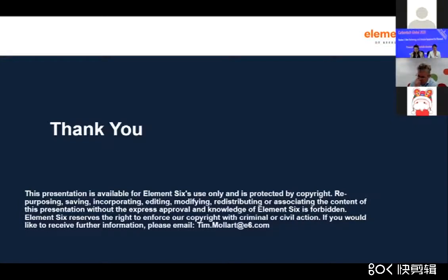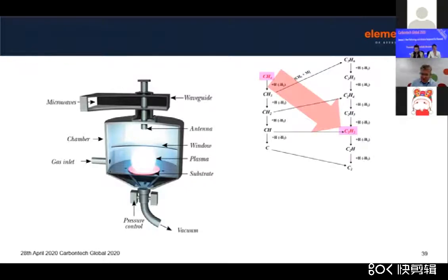Thank you. Well, I think I'll come to a couple of points here. The advantage is that it gives you very high control over the purity of the diamond that you're producing, and for some applications, even in polycrystalline diamond, that is actually very important. And I think the advantage, as the schematic for our reactor would show you, is the fact that it's electrodeless. So essentially, you can reduce the contamination that you get from other types of discharge system, and also, as I say, the intensity of the plasma gives you access to a greater range of plasma chemistries than you would otherwise have.